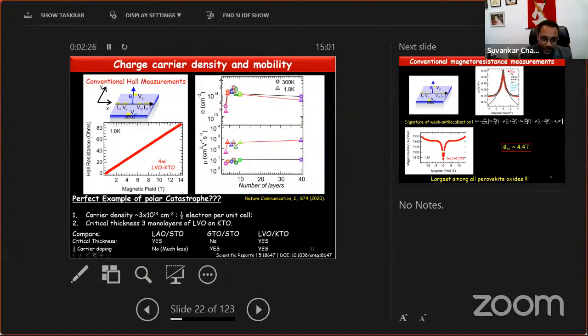Just quickly, I'm telling you one thing: instead of saying why it is showing polar catastrophe, I'm telling you what was the problem in LAO-STO. Once you put this aluminum, it always has a tendency of making the thing oxygen vacant. And LAO has a much stronger reducing growth condition, which makes this strontium titanate oxygen vacant. Although you might have a polar catastrophe scenario there, it could be dominant. You have a mixture of oxygen vacancy and polar catastrophe.